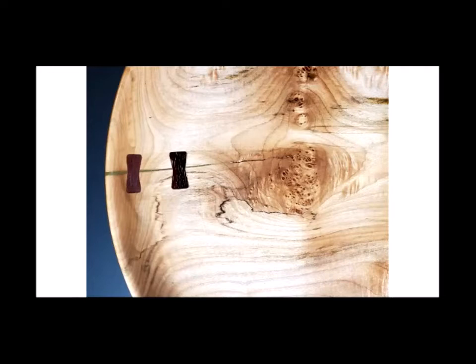with brass powder in it, and I put it in there, and I used a heat gun to get it to flow down into the crack and to make sure that this area down here flowed into that area as well. So it's not very thick. Actually, that's probably almost life size right there. It's a little less than an eighth of an inch at the rim, and it goes down to nothing over here. And because this happened after, I was worried about it continuing to move. So I put a couple butterflies in there, they're functional and also just for the effect.